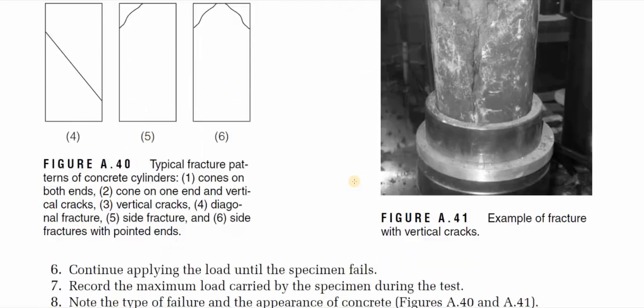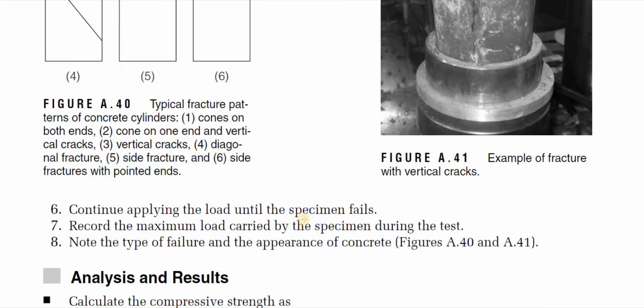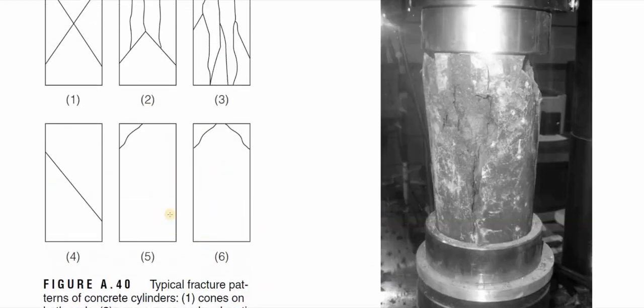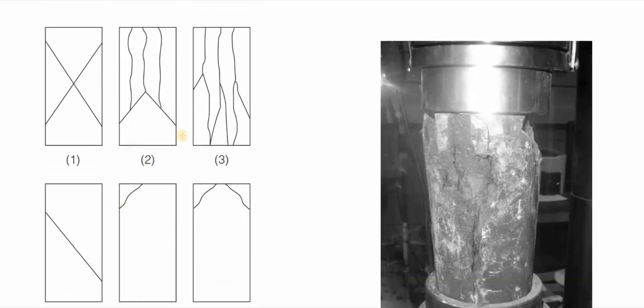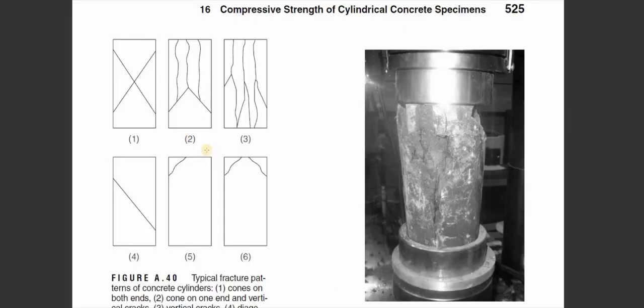After that, continue applying the load until the specimen fails. Record the maximum load carried by the specimen during the test. This is an important issue because you need to know the maximum load. And number 8, note the type of failure and the appearance of the concrete. Let's see the types of failure as shown here. We have 6 main types of failure. Let's zoom out, yes, here.